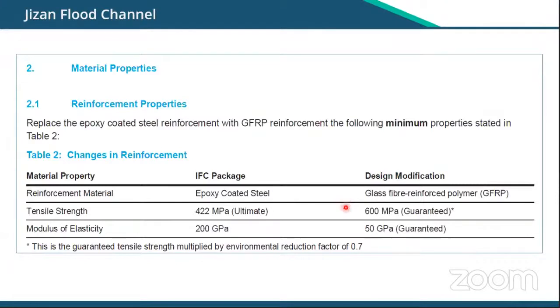On this table, you will see the original design epoxy coated on the left, and the GFRP alternative on the right. You can see that epoxy coated was considered with a tensile strength of 422 MPa, modulus of 200 GPa. The GFRP material here was needed at 50 GPa, and they considered 600 MPa. The 600 MPa, you see the comment, is already factored with the environmental reduction factor of 0.7. As per ACI code, 0.7 is today the factor applied to consider the alkali resistance and accelerated aging. And of course, in the design, we will also be sure that we don't go beyond 55%, the creep factor. That's also governed in the ACI design.